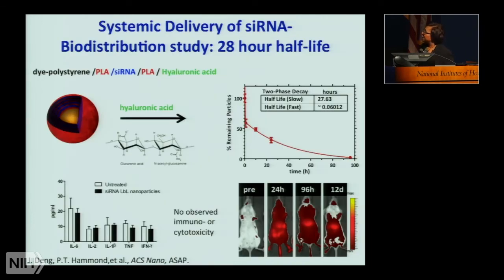So what we began to develop then was a 4-layer nanoparticle. We would start with a core nanoparticle, and then we'd layer poly-L-arginine, siRNA, poly-L-arginine, and hyaluronic acid, plus, minus, and that would be our outer layer system. We found that when we generated these nanoparticles, we got very nice blood half-lives. This is key because we need a long residence time in the bloodstream to allow nanoparticles to accumulate in the tumor. In this case, we found that we had a 28-hour half-life, which is actually quite extended for these kinds of nanoparticles.